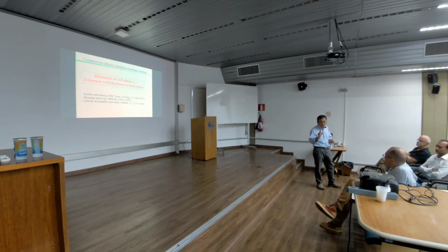In order to make the exchange coupling take place, you have to reduce the soft phase dimension to twice the domain wall thickness. That was calculated in the early 1990s by three groups of theoretical calculations. So this is the important step. Why? We are forced to go to the bottom. What is the bottom? The bottom is the nanoscale. When I started my magnet research on neodymium iron boron magnets, the grain size was 30 microns. That's the lowest grain size we could reach. 30 microns, 30,000 nanometers. You see the orders of difference. Now you need nanometers, because the domain wall thickness is a few nanometers. That's the physics.